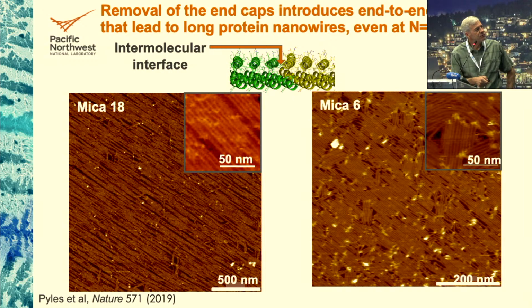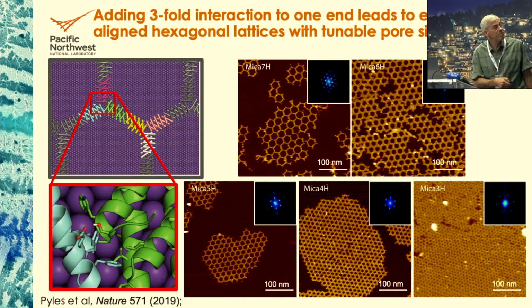If we now introduce an interaction at the ends of the protein, so the ones I just showed you can't bind to one another at the ends, but if we allow them to bind, even in a hydrophobic interaction, we now get single protein-wide nanowires that cover the entire surface. And if we build in a threefold interaction at one end and leave the twofold interaction at the other, they self-assemble into a hexagonal network, co-aligned with the mica lattice, where the pore size is defined by how many repeats we put in the protein. Truly a remarkable outcome, okay?